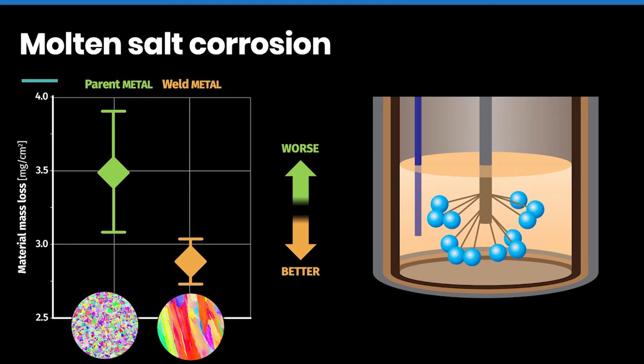If we want to understand this result, we have to look into the micro scale. And indeed, we found that the microstructural differences between these materials is the main reason for this observation. So we found that the large amount of interfaces between variously oriented crystallites in the parent metal accelerates the dissolution of the parent metal into the molten salt. While in the weld metal, we have significantly larger crystallites, which leads to significantly smaller amount of interfaces. And that's why the weld metal has better molten salt corrosion performance than the parent metal. So from these results, we found that the weld metal is not only stronger, but it also has better molten salt corrosion performance and can be thus safely used in molten salt environment.